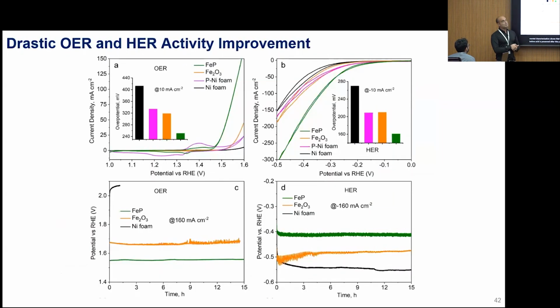And when you look at the performance, that's actually quite stunning. Black is the nickel foam. Nickel is actually a catalyst, not much, okay. We phosphodize the nickel foam, nothing happened. We put the iron oxide, looks a bit better. We convert it into phosphide, boom. Amazing, right? So we can increase dramatically the OER and HER activities, OER, HER, all over metals.